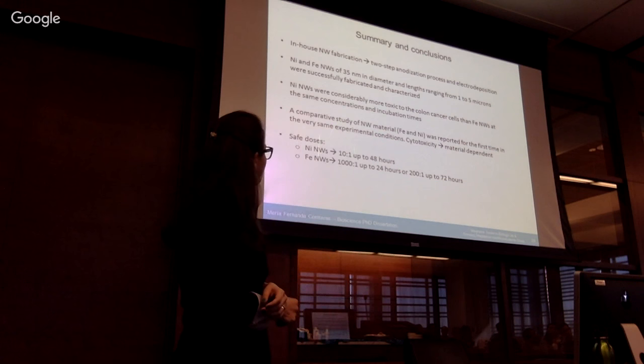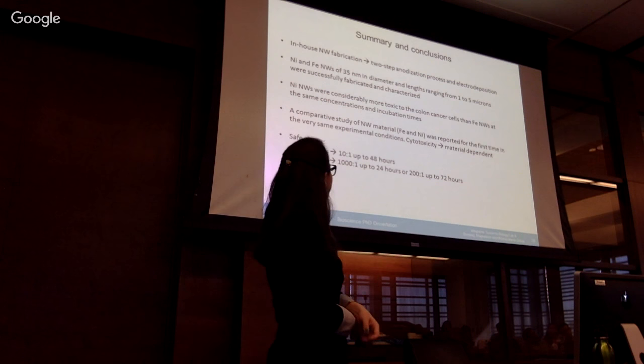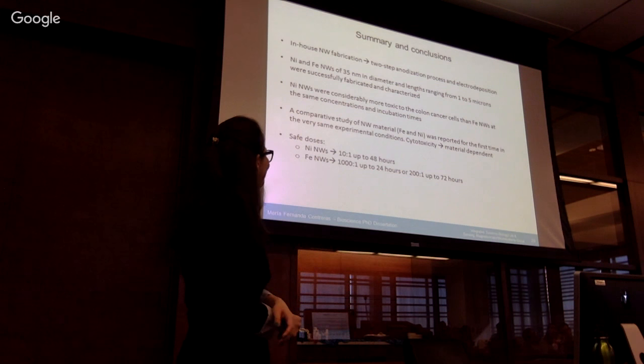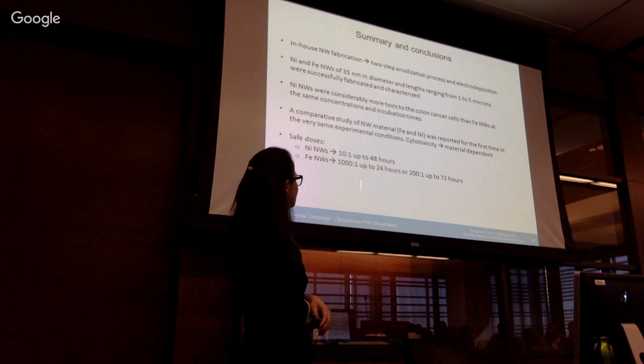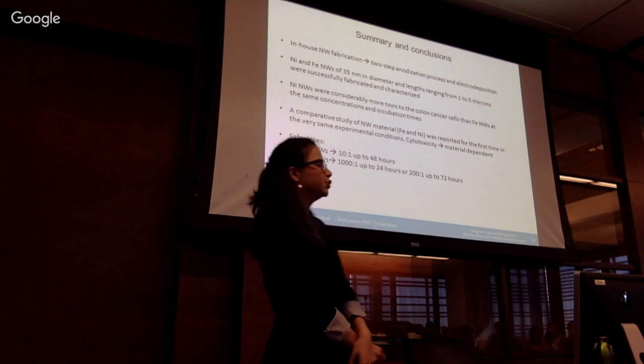We found some safe doses for both of the nanowires for nickel. They were safe at a 10-to-1 concentration up to 48 hours. For iron, we have a considerably larger range of tolerance in terms of concentration and incubation time. So you can add up to 1,000 wires per cell for 24 hours or 200-to-1 up to 72 hours.